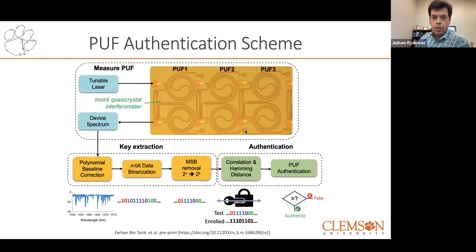So if we want to authenticate many different devices, we just need to measure their spectrum and store that in a database. The grating coupled measurements are a highly automated process. This is done in silicon processing, wafer scale. It's highly automated. So we think this is a potentially scalable technique to be measured at package, after packaging. But let's say we take our spectrum and we need to digitize it. We have a few tricks here where maybe we remove the most significant bit, but we do some type of analysis. In this case, we'll do a cross correlation between two keys and determine if it's authentic or not.